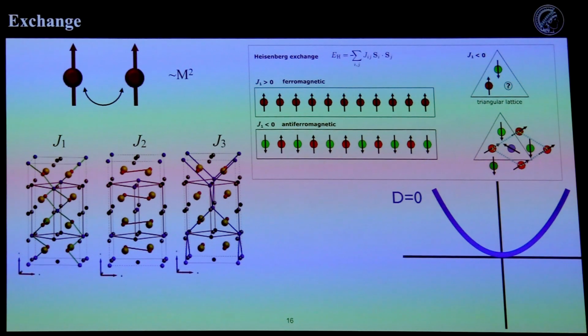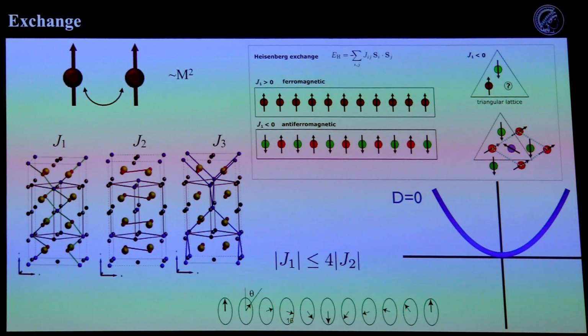And what this does is it actually creates your non-collinear texture. So this guy always wants to be ferromagnetic or antiferromagnetic. This guy wants to be ferromagnetic, and then this guy wants to be antiferromagnetic. And what this causes is when there's some competition between these two, you can create spin spirals and non-collinear textures. But it depends on how strongly each one fights. And they have to be a little bit better than Conor McGregor to actually start to create these spirals and things like this.